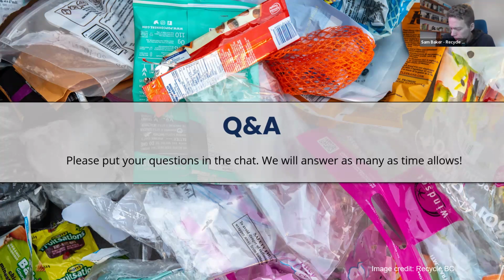So we did a pilot about 2 years ago in a municipality in Vancouver, where it was a curbside set-out of a segregated stream. So put it all in one bin, its own bin. And there we saw a capture rate 3 times higher than what we get at the depot. So while the depot is great and allows us to keep this material segregated and therefore reduces the processing cost significantly, it's just not convenient enough for the resident to get those high capture rates that we as PROs need to meet our targets.